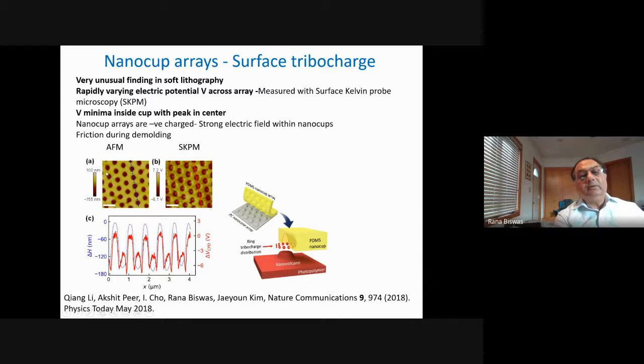So you first, of course, look at the AFM, atomic force microscopy results. And if you traverse over this blue line over here, you see the trace of these nanocups. So it's about a depth of 160 nanometers, as you expect. So this is the flat portion, and this is the bottom of the nanocup. So there's no surprise there.